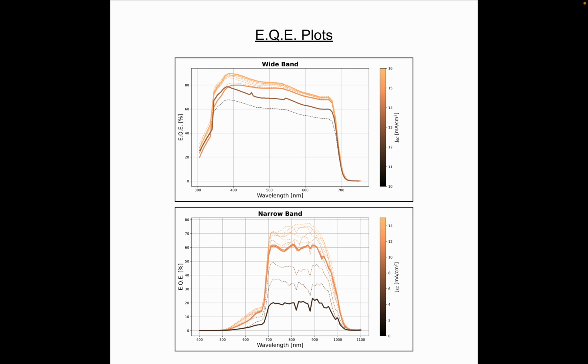What's more interesting here, though, is the EQE. And this is super cool because it's one of the higher regarded types of efficiency measurements in photovoltaics, where we can actually separate those two different layers and measure them differently based on their light compositions. And this was key because this told us our devices were doing pretty well, and we had measured them in this new system, but this told us the one thing we needed to tweak. And that, as you can see, is the narrow bandgap layer.